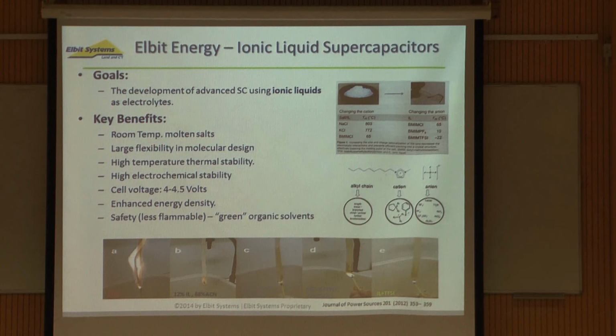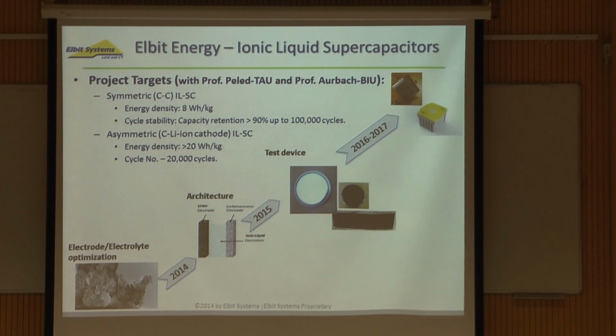And another area that we are focusing on is going into the organic world, but not organic per se, but using ionic liquids, which are advanced green organic solvents that have the ability to have a very high electrochemical stability, up to 4.5 volt. And there are a lot of challenges in terms of the implementation of these ionic liquids, especially because they are very viscous, they have a very good behavior at high temperatures, but a very bad behavior at low temperatures beyond -20 centigrade. And of course the conductivity is a very big issue.